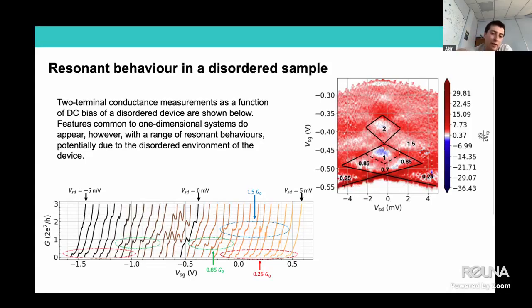But the interesting part here is that, as you can see, there is not much clear phenomena here, because these results that we've observed, we think it's from a quite disordered sample. So we see a bunch of resonance behavior where there are peaks and unexpected phenomena. So this is a transconductance plot where the color represents the gradient of conductance with respect to the gate voltage. So that's the confinement and relaxing of that one-dimensional channel.